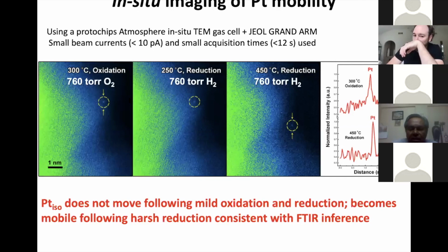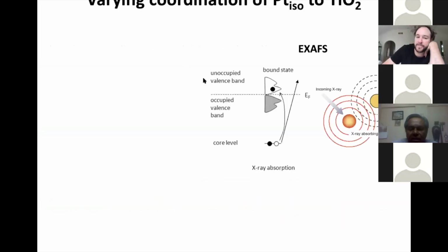So we went in and we wanted to be able to describe how the coordination environment of platinum was changing as we put it under these different environmental conditions, remembering that all of the detailed analysis we had done before was on this condition in the middle here. So to do this, you can use EXAFS. So EXAFS is a part of X-ray absorption fine structure, and this looks at the extended fine structure. And specifically what you're looking at is you have photo-emitted electrons from an absorbing atom that scatter off its neighbor. And when it scatters off its neighbor, it results in periodic oscillations in your X-ray absorption spectra that you can interpret and understand what the local environment is.